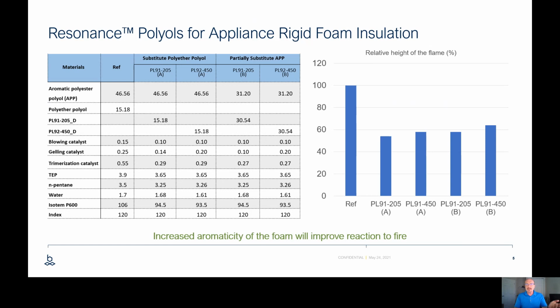You can see in this particular presentation, this particular slide, it's a rigid foam system. We took out the aliphatic polyether polyol, left in more or less the aromatic polyester polyol, and introduced some of our polyols to these systems, and you can see there's a significant drop or improvement in reaction to fire, a drop in the relative height of the flame. This is the DIN 4102 test, or B2 test, as we tend to call it, for these rigid foam systems.